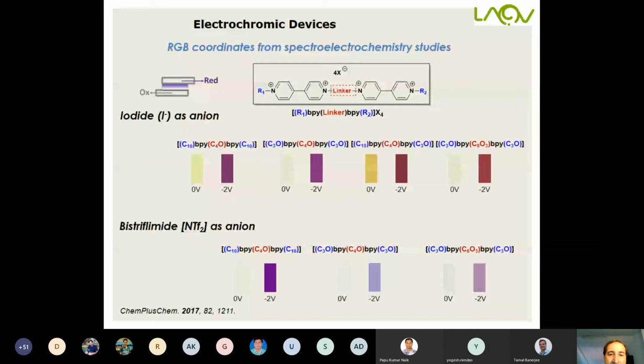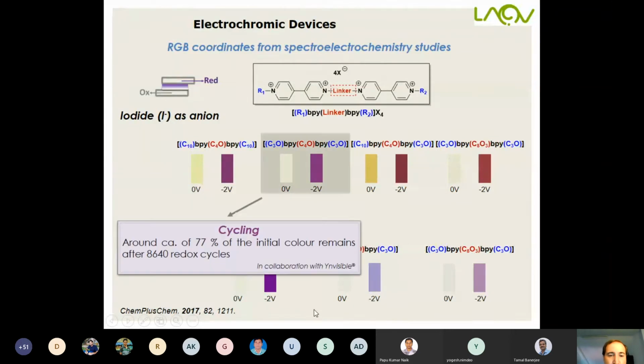More recently, we tried another approach using a linker between two bipyridinium units, and it's possible to extend this system using poly-bipyridinium systems combined with iodide or bistriflimide as anions. Here you can see a variation of colors, and it's also possible to recycle, to show the cycling.